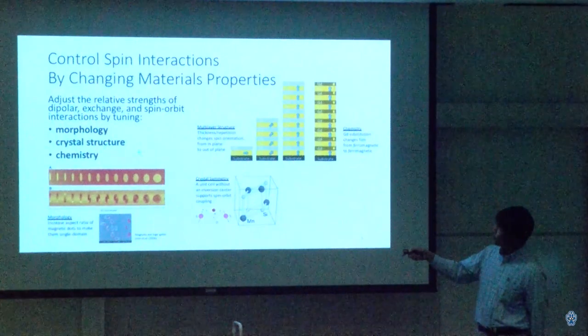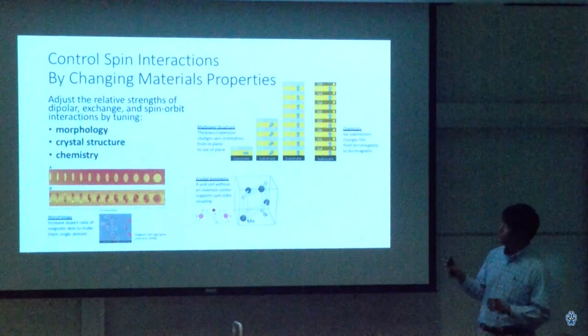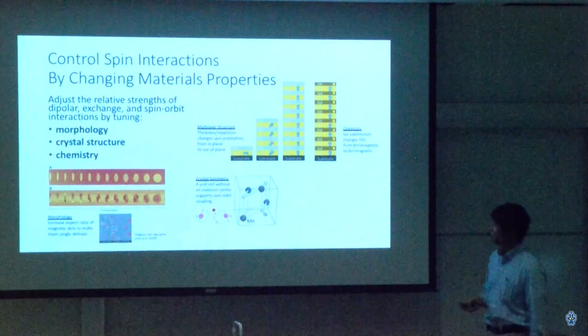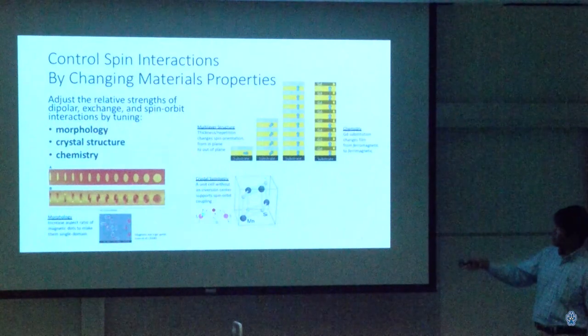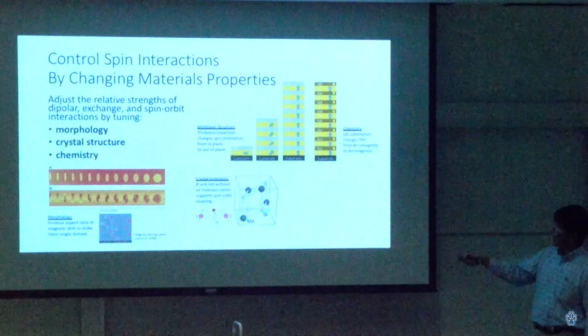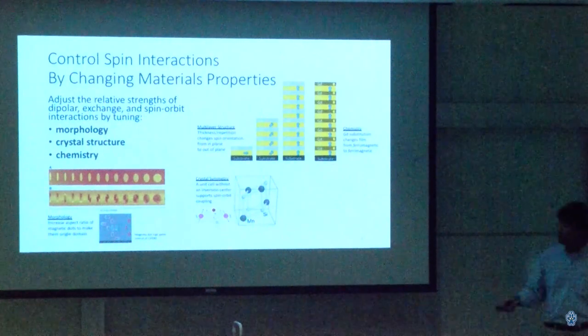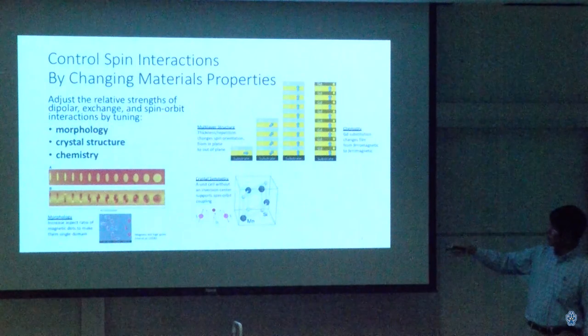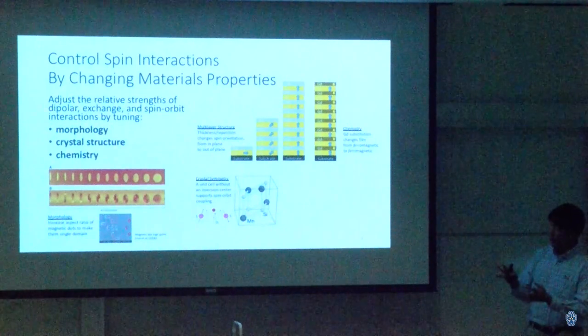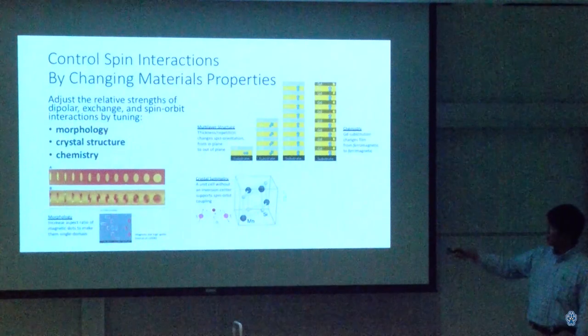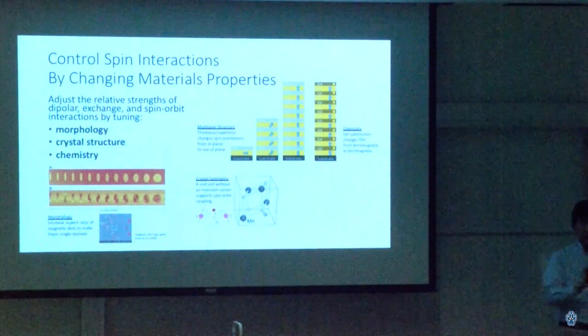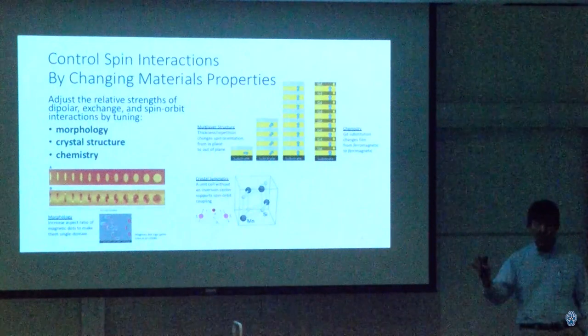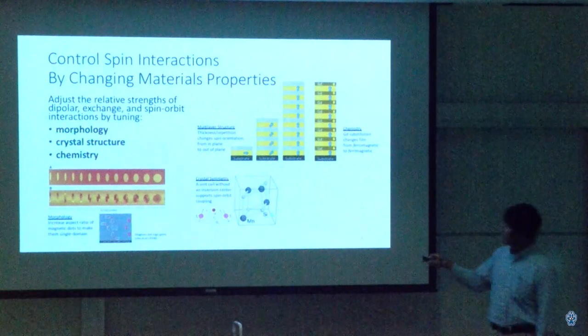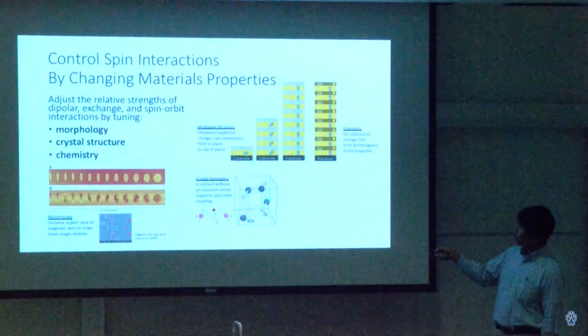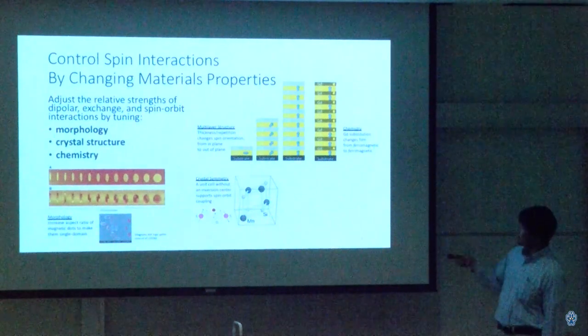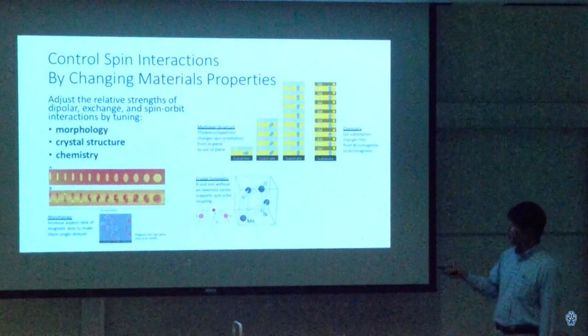You can also change the crystal structure in order to change the relative proportions of the dipolar, exchange and spin orbit interactions. In a natural crystal, in order to change the crystal structure, you have to change the atoms that belong inside the crystal itself. So this is a small segment of manganese silicide. This is the repeating motif that is applied to create a large extended crystal. If you want to change the crystal symmetry, or the crystal structure, it goes hand in hand with changing the chemistry as well. Manganese can be substituted with something else.